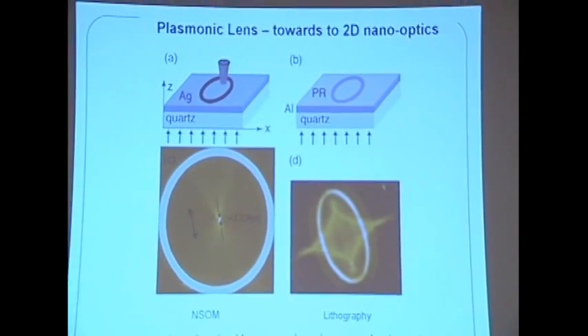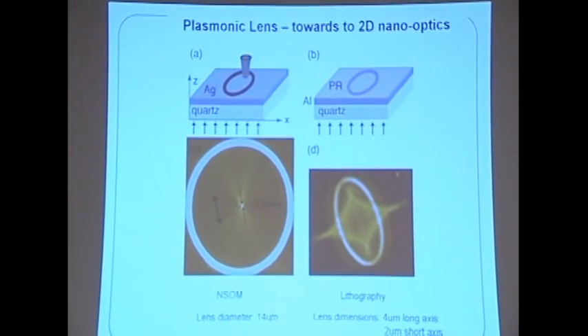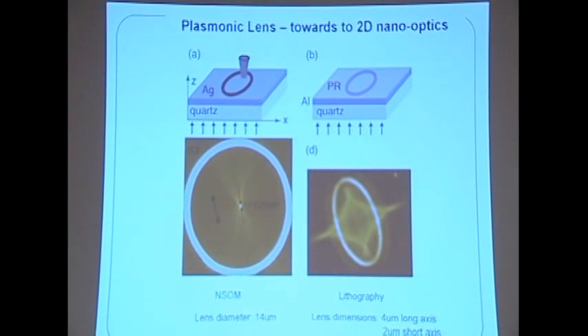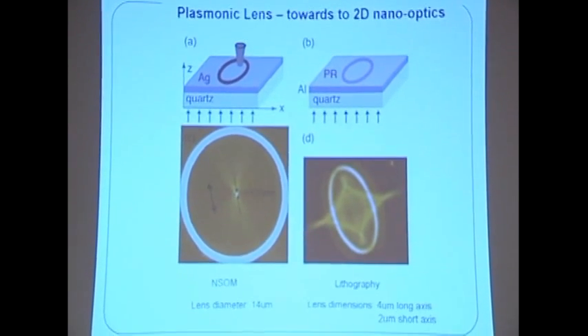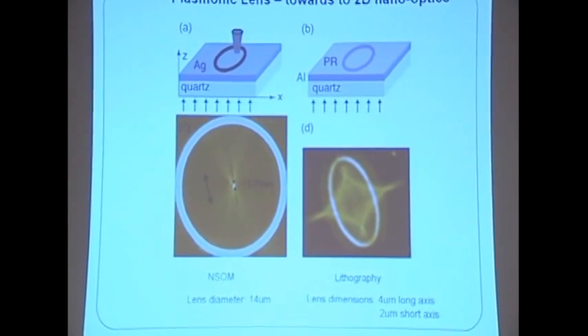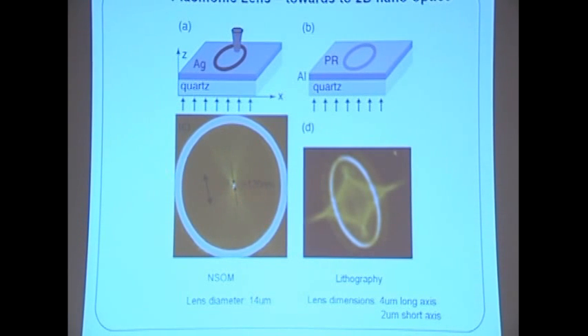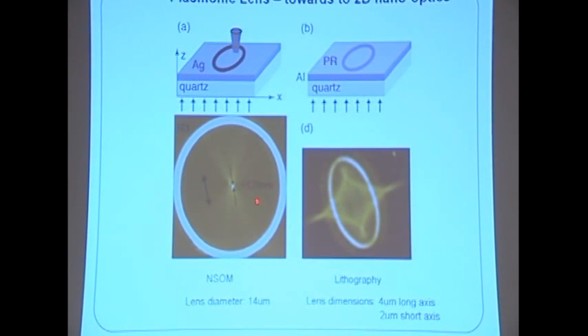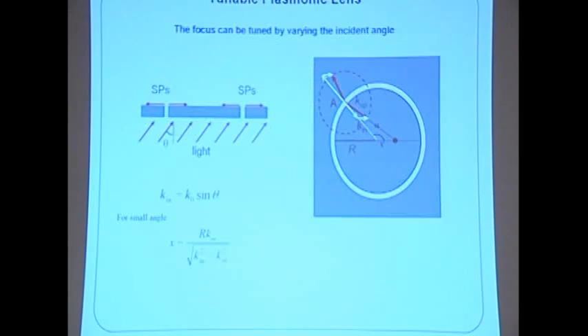This slit works with two functions. One is a coupler to the far field, because the slit provides all kinds of k-vectors. If the k-vector matches the surface plasmon resonance, that launches the surface plasmon wave, a two-dimensional surface wave, essentially. And you see the interference here. And this is the photoresist imaging, which basically shows you the focus.